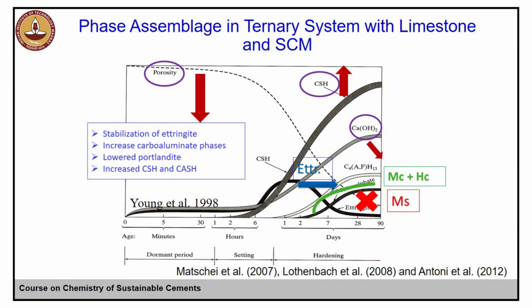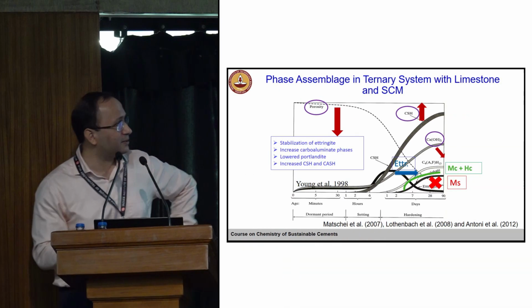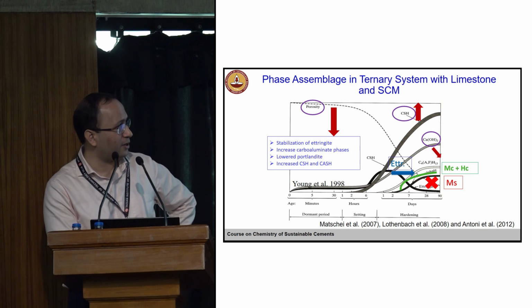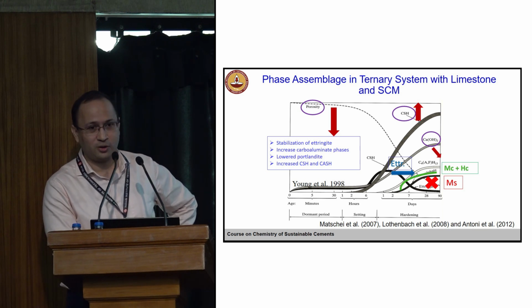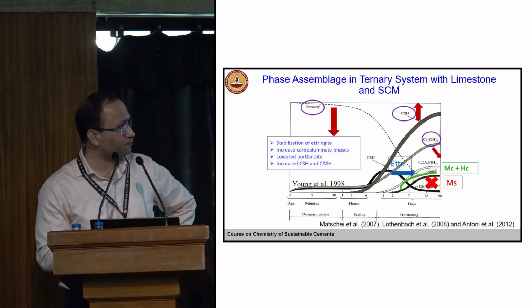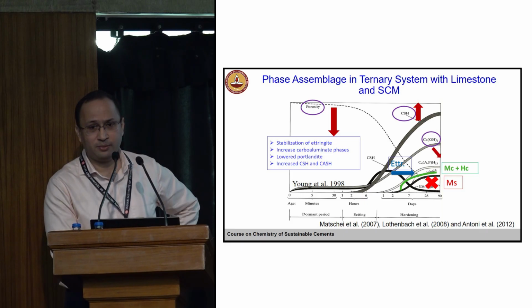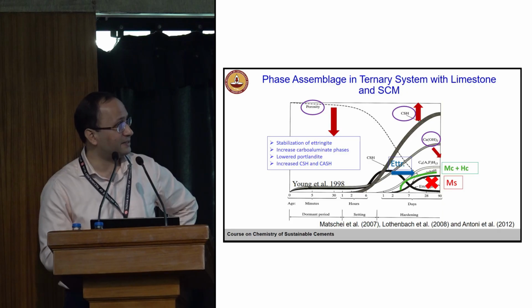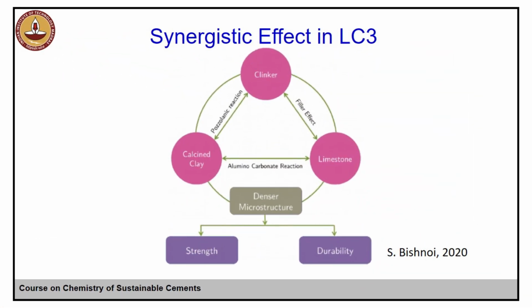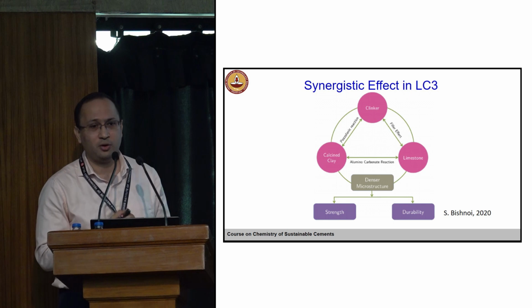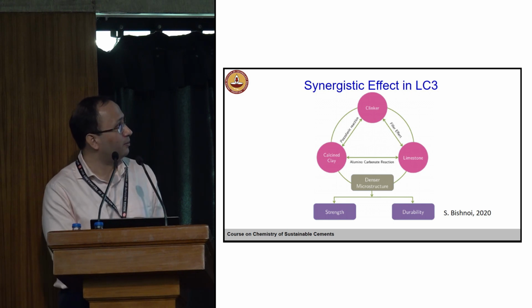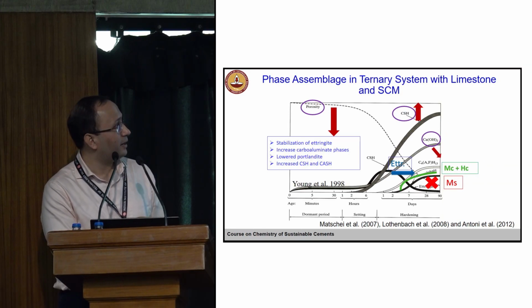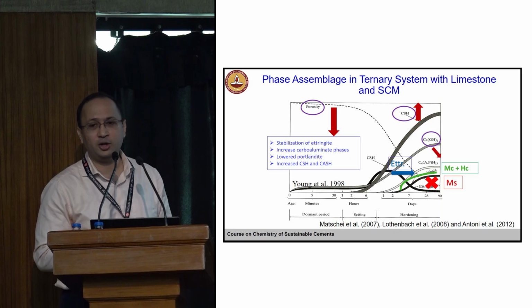Now, what happens when you have limestone and SCM, right? When you have a SCM with limestone in this, traditionally you will have conversion of ettringite into AFm. So you'll have monosulfate forming at the cost of it, because that's what happens. So now in this case, you don't have this, you form additional hemicarbonate and monocarbonate phases, okay? Obviously, because of the reaction, the calcium hydroxide content will decrease because pozzolanic reaction is still occurring, right? Pozzolanic calcium hydroxide will react with your reactive silica alumina, form CSH. So what will happen? CSH will increase. So these kind of changes happen when you have both SCMs and limestone, and overall stabilization of ettringite, right? That's important. Increase in the carboaluminate phases, lowering of portlandite, increase in CSH. So overall, this improves the durability of the system.